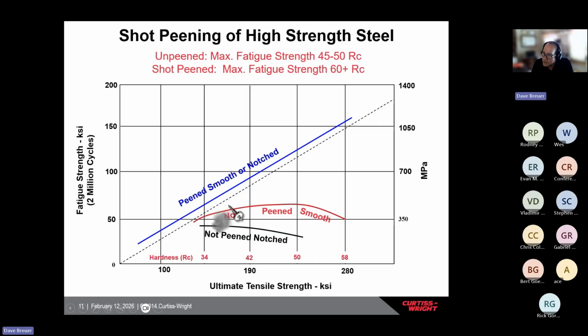And I should have mentioned this curve first, which is the non-shot peen. But what it shows here is that when you shot peen parts, it's better to have the material be harder and higher strength. So you guys probably notice when you go to higher strength spring wire, you get better results. And then when you shot peen that, you're getting more compressive stress from the higher strength spring wire. So you should get like a double bump in performance if you compare a lower strength spring wire to a shot peened higher strength spring wire.